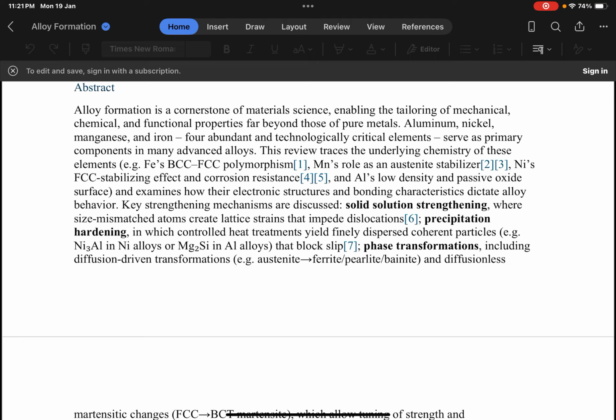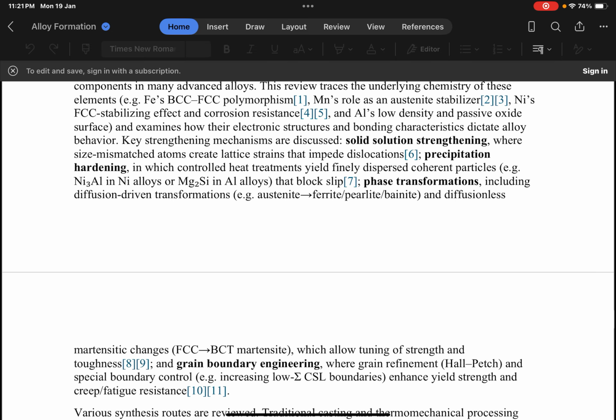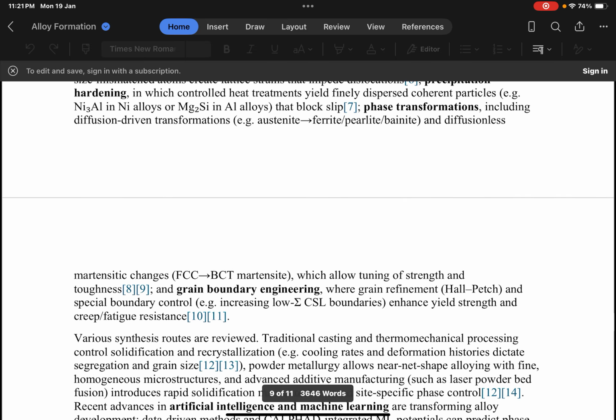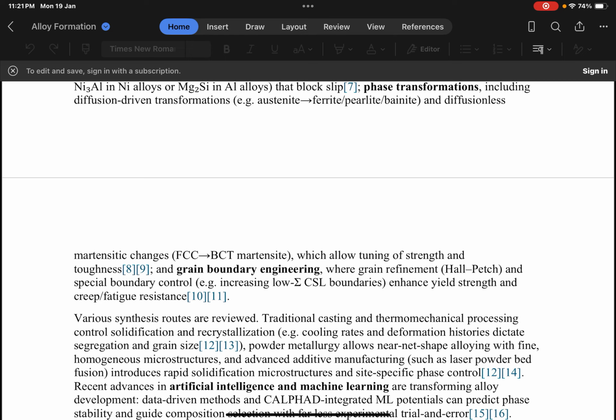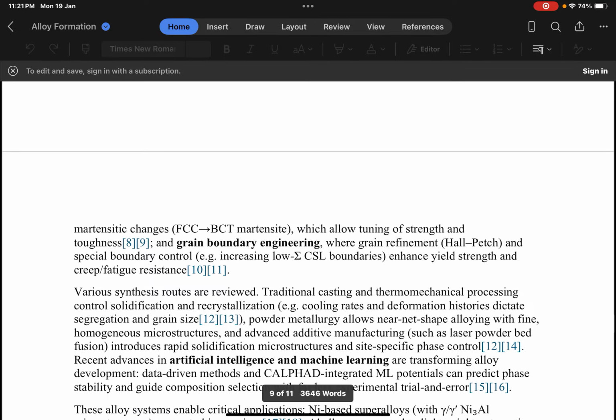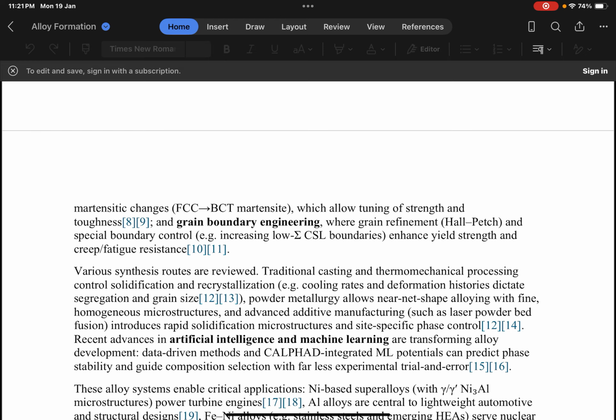Key strengthening mechanisms are discussed: solid solution strengthening, where size mismatched atoms create lattice strains that impede dislocations; precipitation hardening, in which controlled heat treatment yields finely dispersed coherent particles; phase transformation, including diffusion driven transformation; and grain boundary engineering, where grain refinement and special boundary control enhance yield strength and creep fatigue resistance.